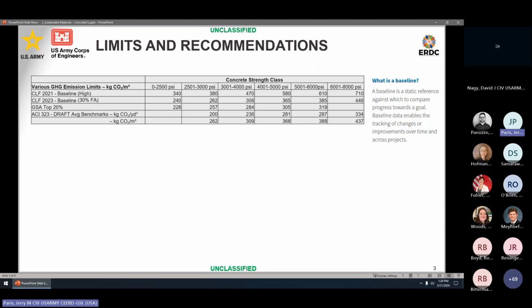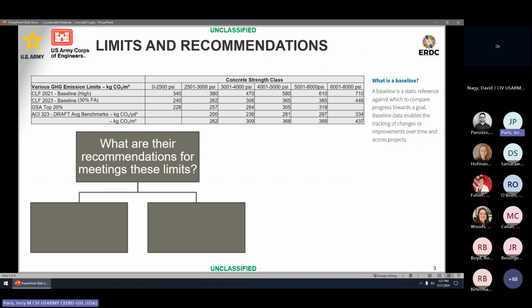And what you'll notice is that these are very, very similar to the Carbon Leadership Forum 2023 baseline values, that 30% fly ash replacement, because they're working from the exact same data set. So all of these numbers should be very, very similar. So the problem that I foresee with this is that as we start looking at these, they are giving limits, but they're not really explaining how to reach these baseline values.